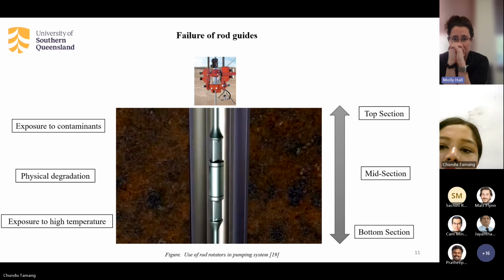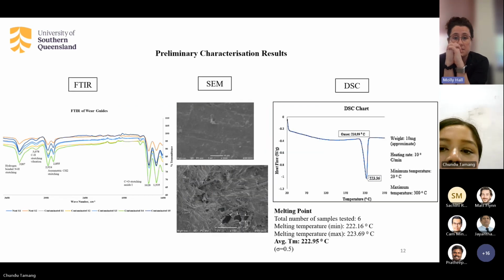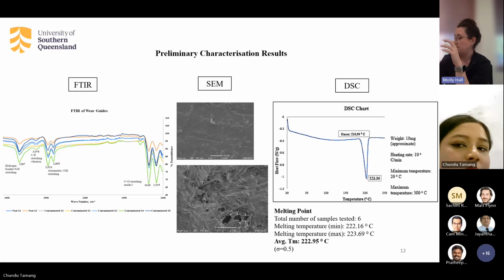And also the lowest one-third section of the well is the one which has the most aggressive solids with higher specific gravity, higher chemical and higher heat exposure. So therefore, it becomes necessary to evaluate the properties of the rod guides and their failure mechanisms according to their location of installation so that we can generate specific location-based data collection and analysis. Now we have conducted a few preliminary characterization tests on 6 randomly collected rod guides from our industry partner, but I need to stress here that we do not have information on the exact location of installation of these guides because they were just collected.